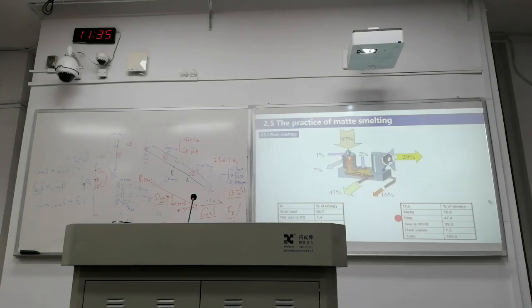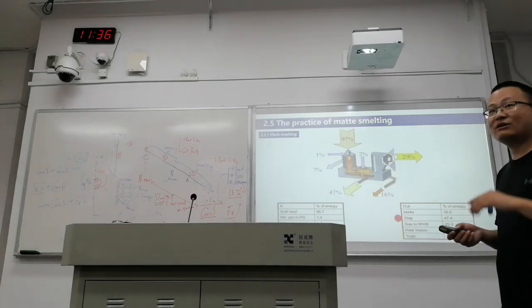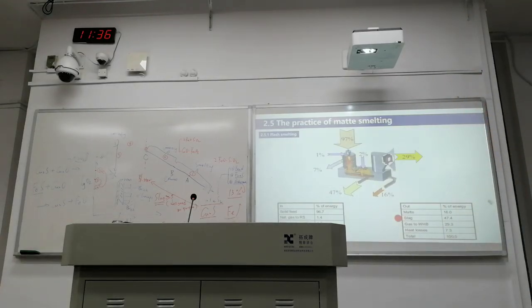So in 1949, the first flash smelting furnace, they were using air and they were adding some fuel to try to produce some energy for the process. But right after the 1970s, when the price of oil increased dramatically, they had to find a solution. So they replaced the air with oxygen enriched air. After that, the furnace is autothermal. Because when we are using air, it is 21% oxygen, right? 80% is waste. They are only taking away energy. But if we are using oxygen enriched air, they are taking much less energy from the furnace. So the furnace energy use can be optimized by 30%.